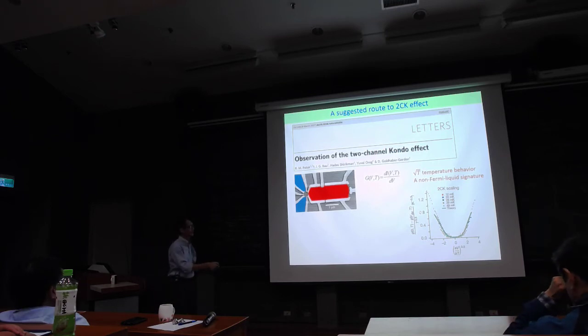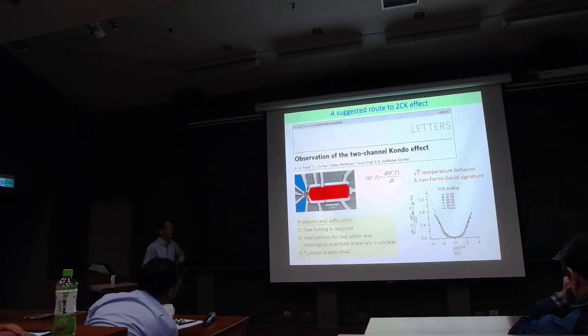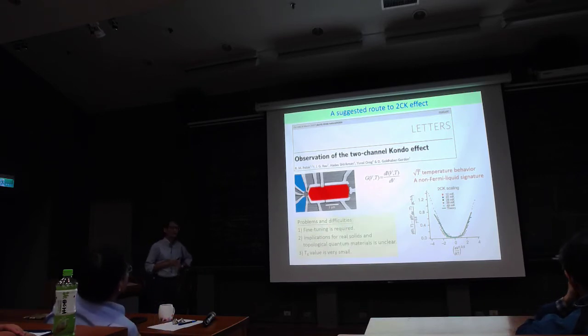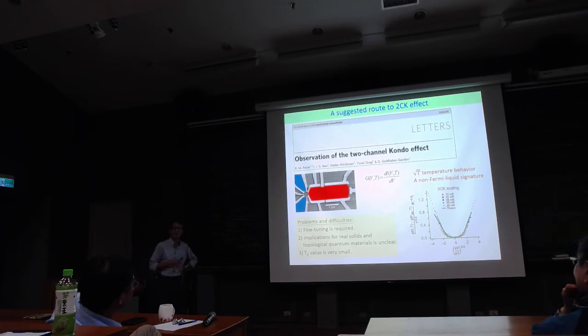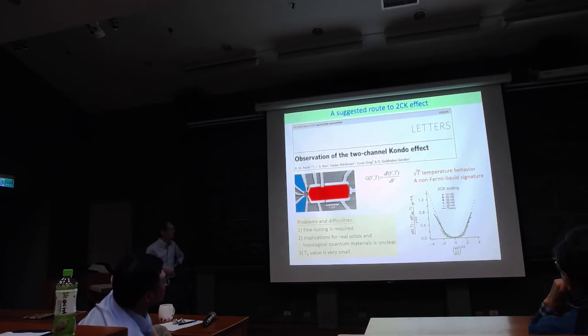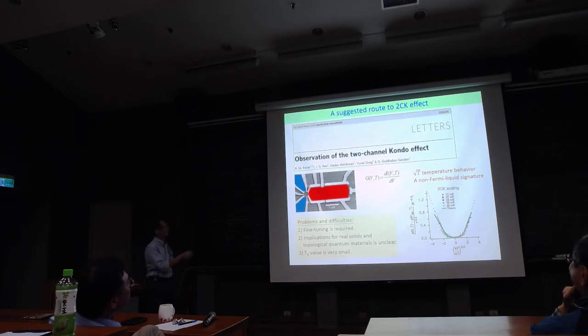So there are some signatures, and maybe they observed it. When we have a Fermi liquid ground state, usually if some physical quantity changes with some perturbation, bias voltage, temperature, or magnetic field, it usually depends on the square of the perturbation, the square of T, or B, or the bias voltage. But in this case, there are theories that when you have some kind of non-Fermi-liquid behavior, you will observe square root T behavior. So yes, square root T dependence. That's what they claim, or they believe they have found the two-channel Kondo effect.